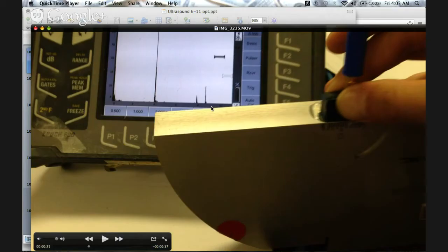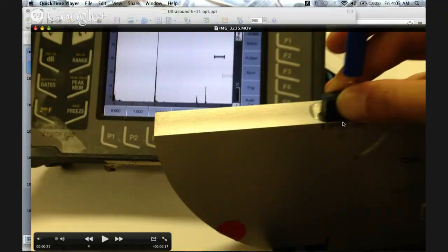And this 8 is actually a second bounce. You see at 5, you have a little notch here. That's because my sound came over here, reflected back into here, and from here to here is 1 inch. So it came at 4, and some of it will reflect at 5. Some of it will go back in and come right back out. 8 is the second bounce, a repetition from this one, and then 9 would be the last hit from here.